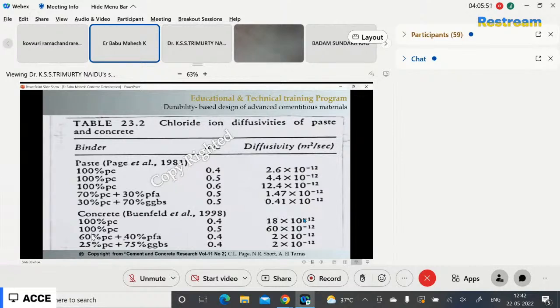At the same time, for concrete made with 100% Portland cement at a 0.4 water cement ratio, the diffusivity of chloride is 18. With a 40% replacement by supplementary cementitious material like fly ash at a 0.4 water cement ratio, the value is 2. The diffusivity coefficient varies by about 80 to 85% in chloride ion diffusivity. Next.